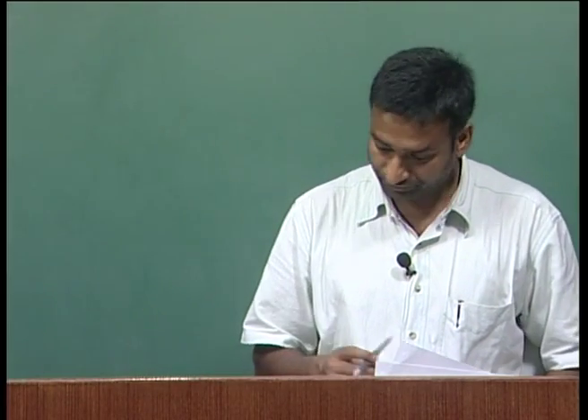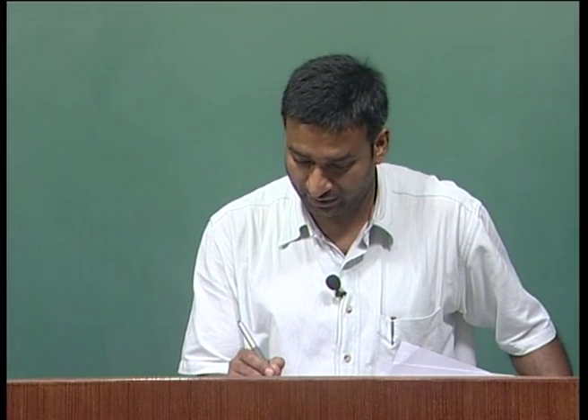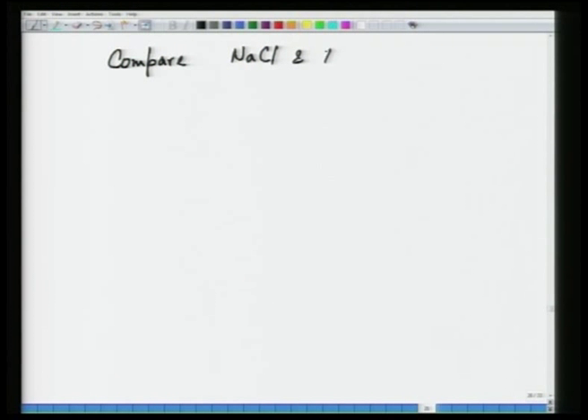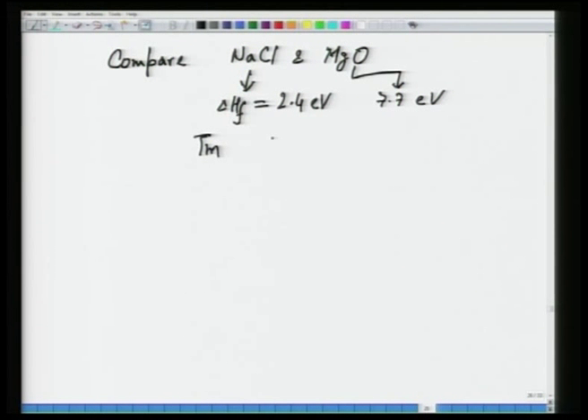Of course, materials with higher bond strengths are going to find it much more difficult to form defects, and similarly, materials with higher melting points will have, at one temperature, lower defect concentration as compared to those with lower melting points, because melting points are related to bond energies. For example, you can make a comparison between magnesium oxide and sodium chloride. So, compare NaCl and MgO. For NaCl, delta Hf is almost equal to 2.4 electron volt, and in this case it is 7.7 electron volt, and this is directly related to Tm. So, Tm of NaCl is about 802 degrees centigrade. In case of MgO, it is about 2825 degrees centigrade.